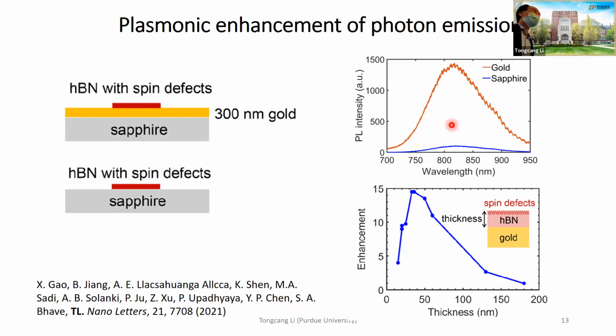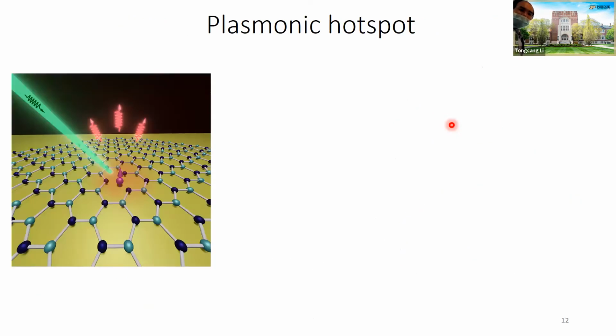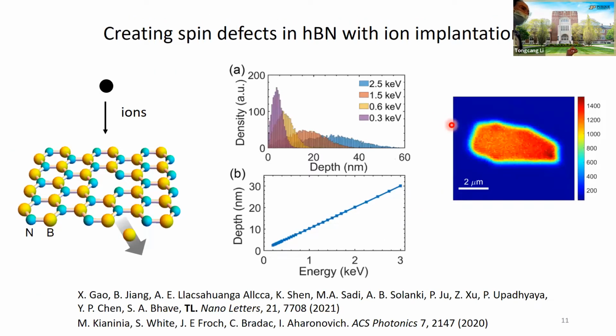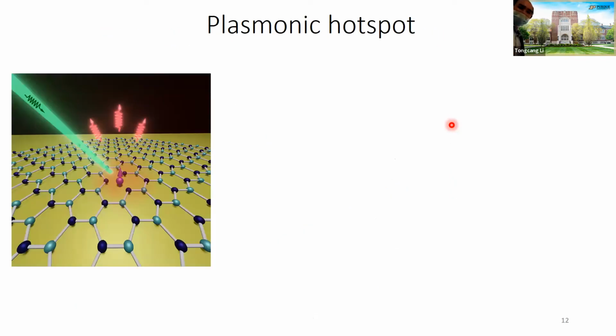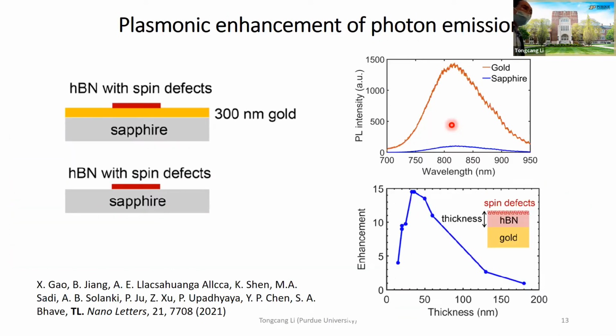How do you generate these defects again, with that broad ion beam? Right. We first generate the defect with the broad ion beam, and then we transfer this hBN flake to gold. How do you know that the defects are only on the surface? Oh, so we basically control the energy. We use low energy ion implantation, so the ions cannot go deep. And then we use AFM to measure the thickness. In reality, we don't control the thickness. We just put the flake there and then use AFM to measure the thickness.